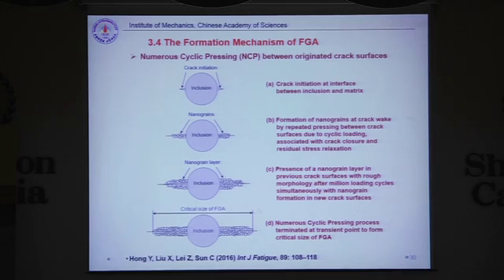It says that first, the crack will perhaps form by the debonding of inclusion and matrix. Of course, there's a kind of localized plastic deformation. And then after the formation of the crack, there will be contacting between the crack surfaces. And this type of contacting will be associated with the crack closure effect and also the relaxation of residual stress. And this process repeats over millions of cycles of loading. So this is the main concept of our model.